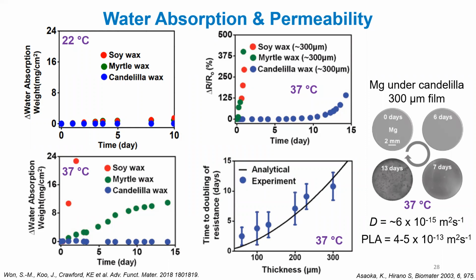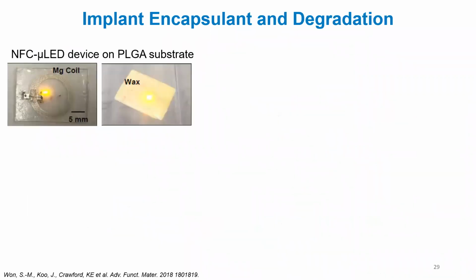And so we determined through estimating that the diffusion coefficient should be somewhere around 6 times 10 to the minus 15 meters squared per second. And then as a comparison, to give you some frame of reference, PLA, polylactic acid, is a very common encapsulation material for transient devices. That is about 10 to the minus 13 meters squared per second. So it's a really good barrier material. We're going to see if we can use it in some of our transient devices.